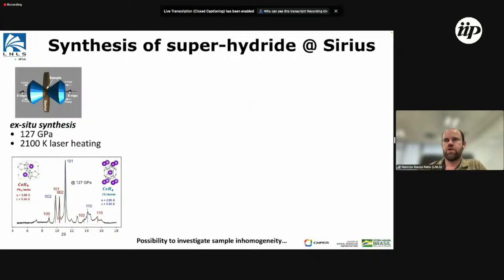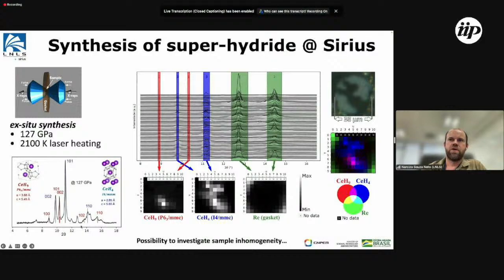And so after we do all that, the combination of those things, that is one thing that we did recently in our new station here at Sirius. We put the material inside the diamonds, in this case a cerium hydride, and we synthesized this cerium hydride, this high temperature superconductor. If we look here on the right, that is a picture of the sample in a microscope that is 38 micron wide. The sample is across a hole that is 38 microns.